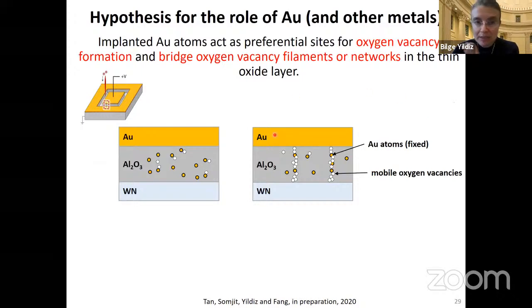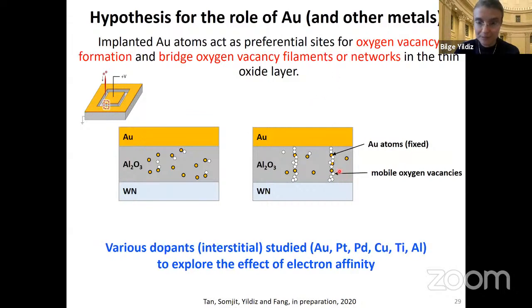And our hypothesis is that milling through the gold implants gold atoms into the alumina. And gold being a high electronegativity element makes it easier to create oxygen vacancies near it. And this may be one way to localize preferential paths for formation of conducting filaments. And with the same argument, we can then hypothesize high electron affinity metals such as gold, platinum, and palladium can improve the repeatability by localizing oxygen vacancies, whereas copper, titanium, and aluminum, regular transition metals, should not do it.